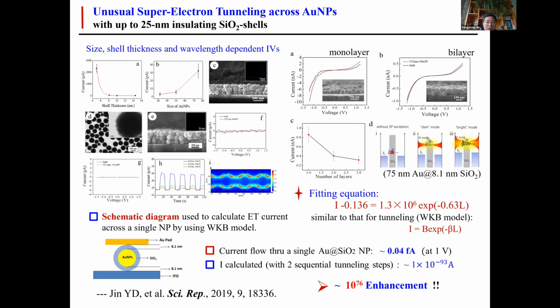We also did some simulation and also performed size-, shell thickness-, and wavelength-dependent IVs. The results show that the fitting equation was fairly similar to that of classic tunneling. But there is a fairly huge enhancement in tunneling properties.